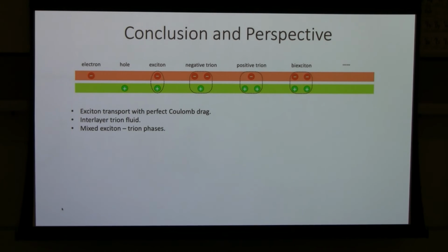Okay, with that, I come to my conclusion. I hope I have shown you that atomically thin semiconductors are a very nice platform to have both electrons and holes, so that you can have competition between attractive and repulsive Coulomb interactions. We can see that the interlayer exciton is tightly bound and is a very well-defined composite. It shows perfect Coulomb drag, because the electron and the hole need to move together, even for an exciton gas without an exciton condensate. And I also showed that you can form a 3-particle trion state, and you can have a mixture of exciton and trion states.